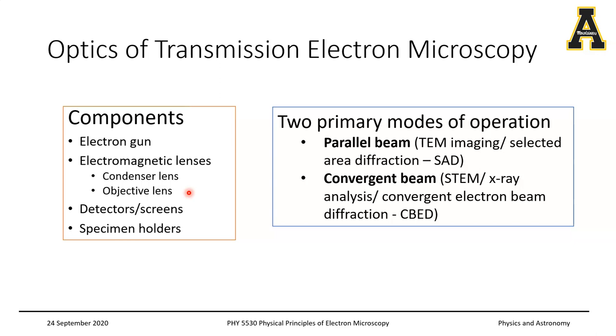The primary modes of operation of TEM are either the parallel beam mode or the convergent beam mode. Which mode you're going to use depends on what you are trying to do with the specimen and what is your interest in that particular investigation. If you want to do a transmission electron microscope image of a sample, you would use a parallel beam, whereas if you are doing scanning transmission electron microscopy you would need a convergent beam. Any kind of x-ray analysis you want to do with the TEM would also rely on the convergent beam mode.